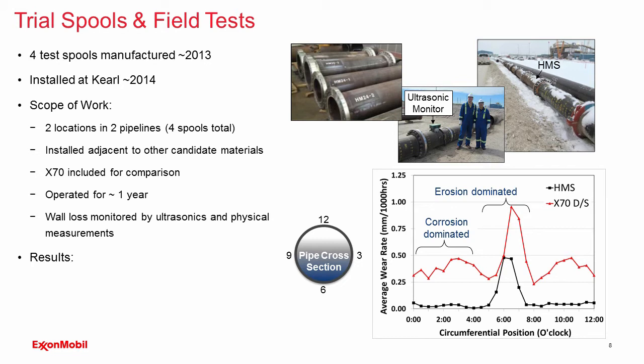At the 6 o'clock position, where erosion dominates, you can see that high manganese, yes, there is some wear, but it's performing much better than the X70 material. And then where corrosion is the dominant mechanism, closer to the 12 o'clock and a little bit adjacent to that, the high manganese steel has barely seen any wear at all after 1 year of use, performing very well. We conducted a life cycle cost analysis looking at all the factors, the cost of the material, the maintenance of the material, and our conclusion was that high manganese steel, this particular grade, was superior to all of the other materials tested in this field trial.